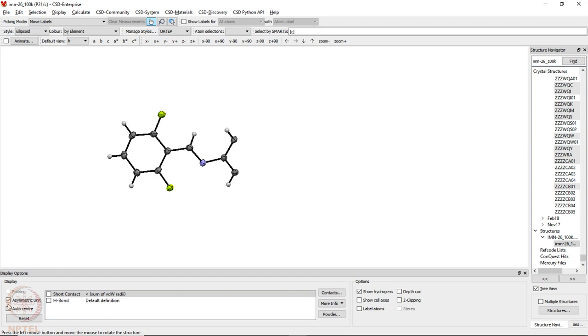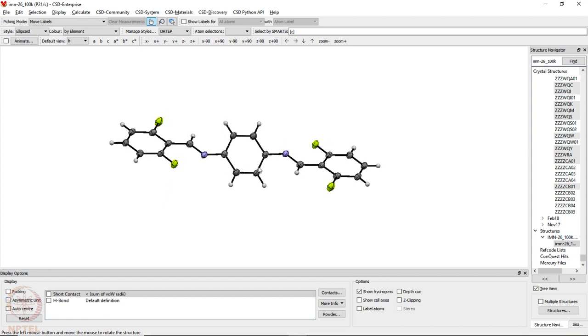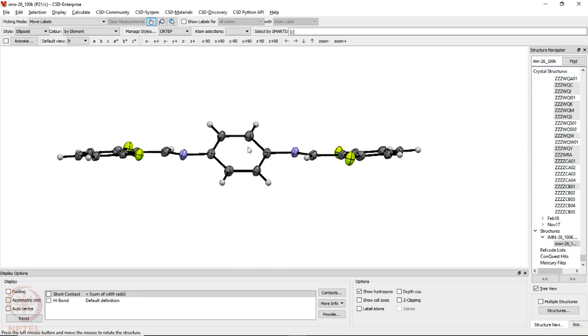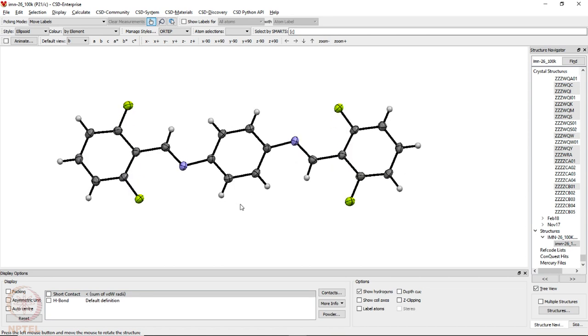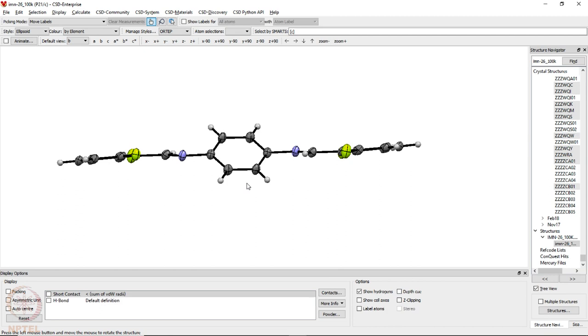So now, this is the structure that we have solved from single crystal X-ray diffraction data. What else can we do with it? See, a single crystal is grown from a starting bulk material that was a polycrystalline powder to start with. What we have done is taken that powder, dissolved it in a particular solvent, and then tried to evaporate the solvent slowly at about 4 degrees centigrade in a refrigerator or at minus 20 degrees centigrade in a refrigerator.